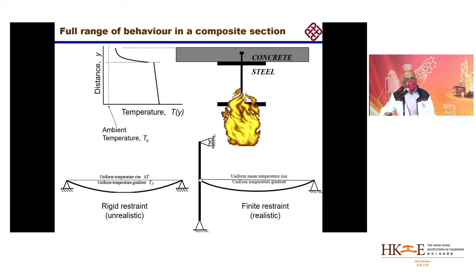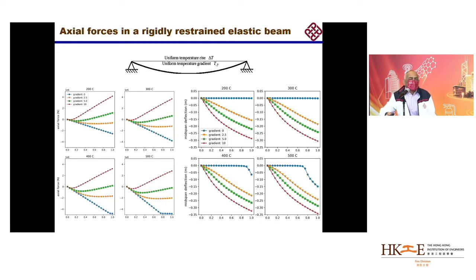Basically now, you saw that picture before, this concrete steel composite. This is the material aspects as well. So I'm trying to see what is the full range of behavior that we see in these composite actions. The left is the rigid restraint situation, but this is not realistic, because typically you have columns and the beam. Depending on the flexural stiffness of the column and the flexural stiffness of the beam, you get different levels of restraint. So if you have infinite restraint, you get this behavior.